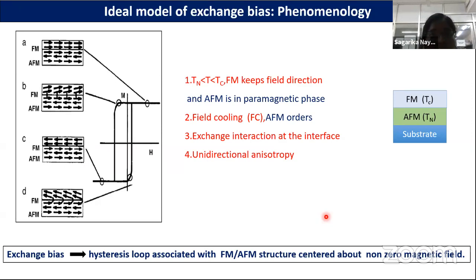First, the ideal model of exchange bias was given, in which the interface is fully uncompensated. In this figure, the ferromagnet is well ordered and the antiferromagnet is well ordered, but the interface is exchange coupled completely parallel, meaning J greater than 0. So it is fully uncompensated. When you do the magnetization reversal, because of this exchange coupling at the interface, these ferromagnetic moments take a very high magnetic field to reverse to the negative direction, because they must overcome the interfacial exchange coupling.